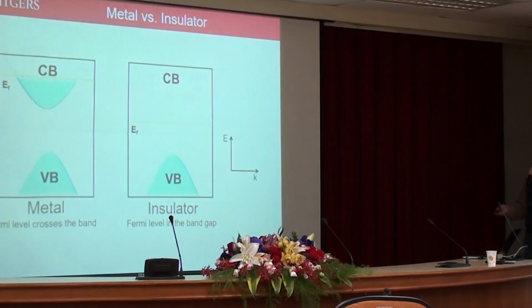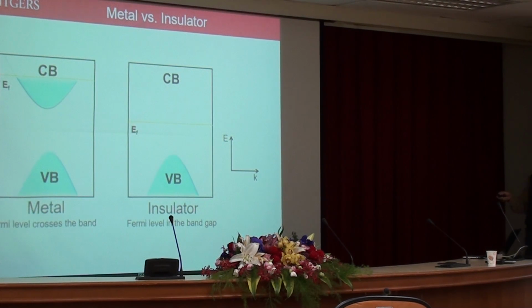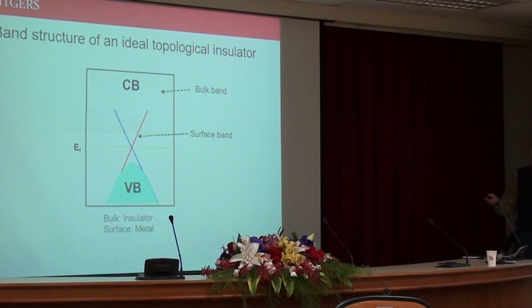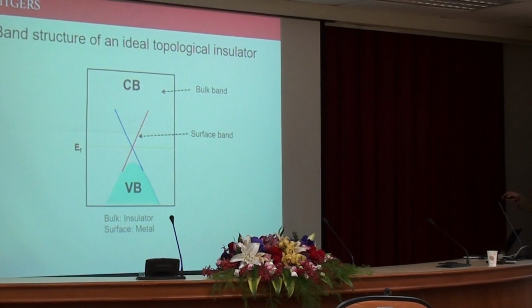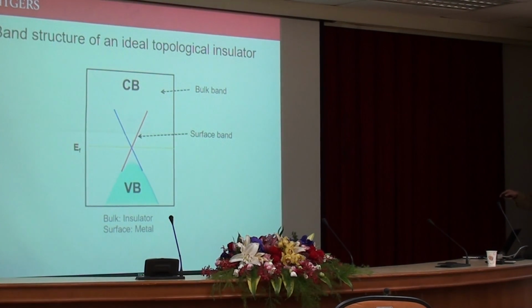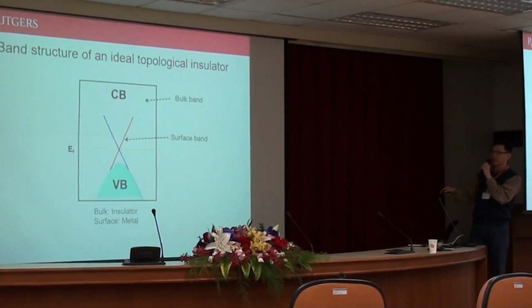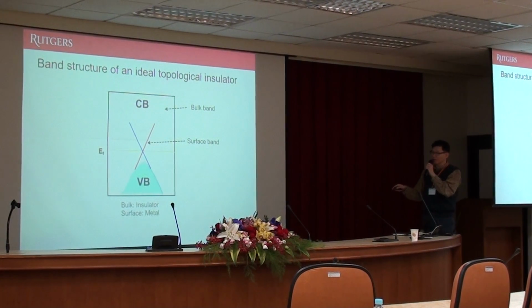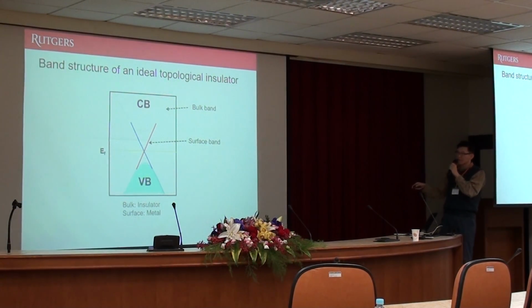The problem is, we know the metal. What is metal and what is insulator? Well, metal is if you have a Fermi level crossing the state, the band, then that's metal. But if you don't have any state where the Fermi level crosses, then that's insulator. That's what metal and insulator is at 0 temperature. But the reason topological insulator is special is because it has this surface state, which originates from the different topology of the material itself. Ideally the Fermi level should be at this Dirac point. If you view this as the bulk band, and this is the surface band, then the surface band is in the gap of the bulk, so bulk is insulating. But the surface state is conducting because the Fermi level crosses the surface band. So this is the ideal case.